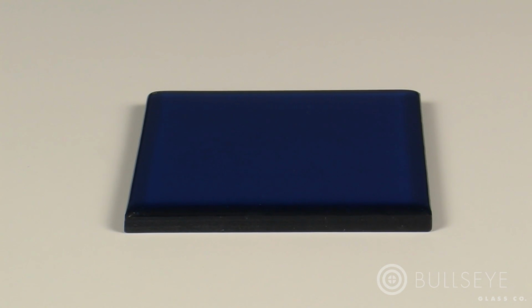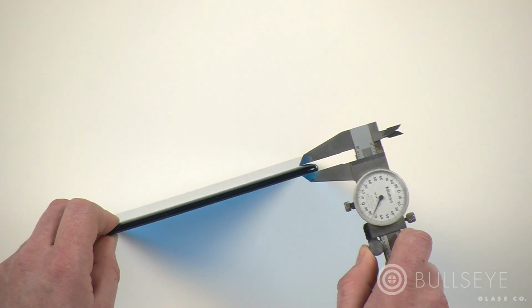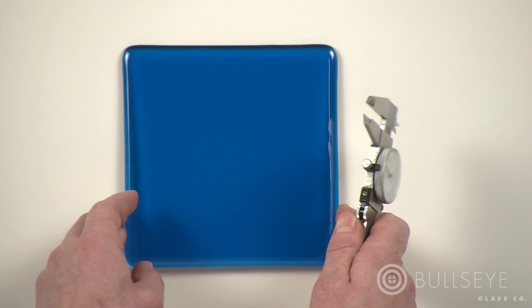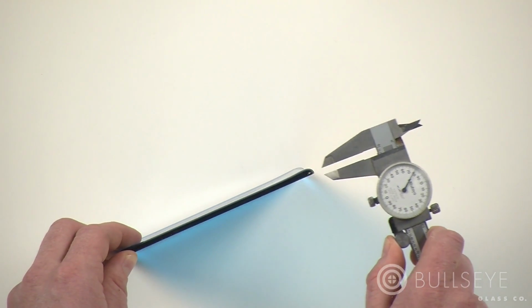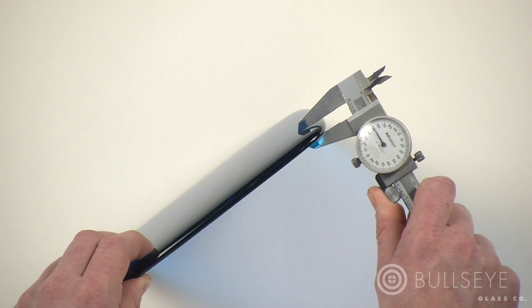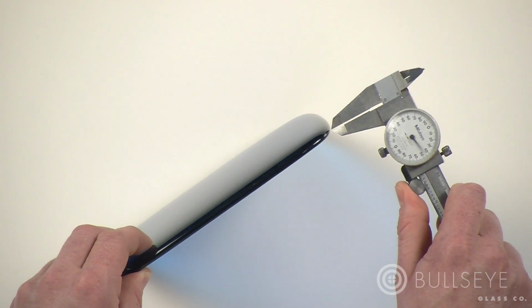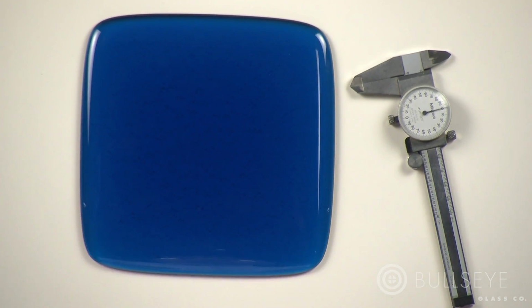As heat within the glass increases, viscosity decreases, allowing gravity and/or surface tension to deform the glass. At full fuse temperatures, Bullseye glass will assume a thickness of 6 millimeters. We call this the 6 millimeter rule. If you fire less than 6 millimeters of glass, surface tension will cause the material to pull in towards the 6 millimeter mark. If you fire more than 6 millimeters of glass, the stack will flow outward toward a thickness of 6 millimeters unless it is constrained by dams.